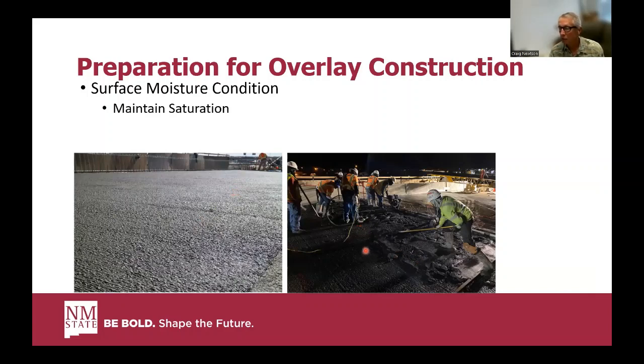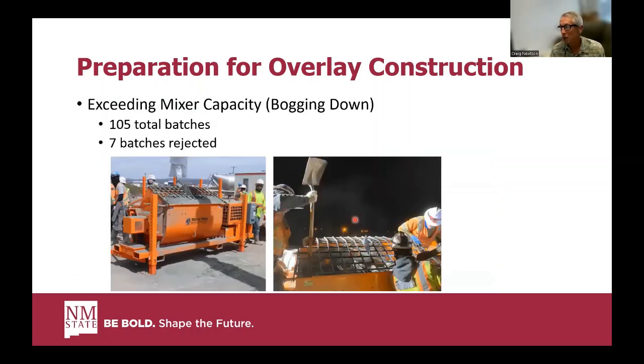Construction began in one corner of the bridge, and once construction started, for the most part, that progress was good. There was an issue at the very beginning with some ponding, but aside from that, it went smoothly for the most part. There were 105 batches of UHPC produced. Each one of those batches was a little bit more than 3/4 of a cubic yard, so 0.77 cubic yards, which kind of gives you an indication of how big the project was.